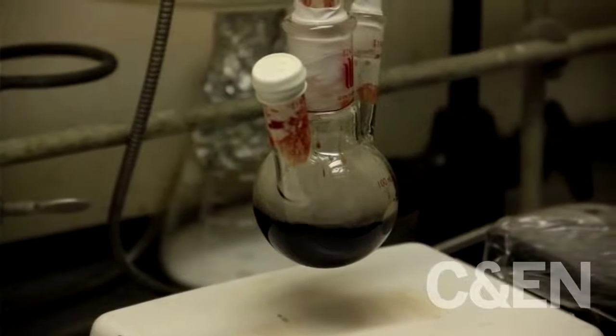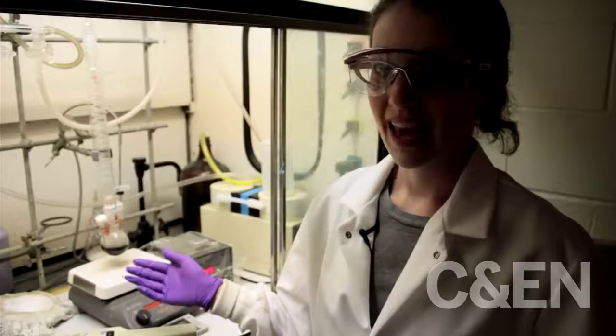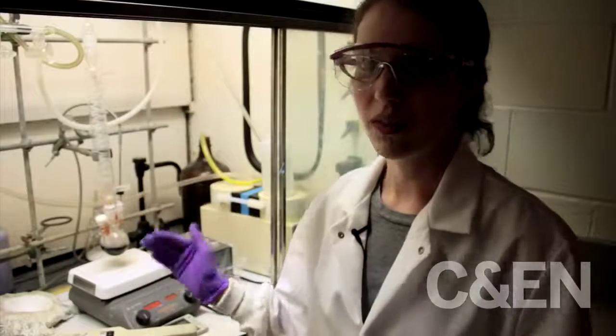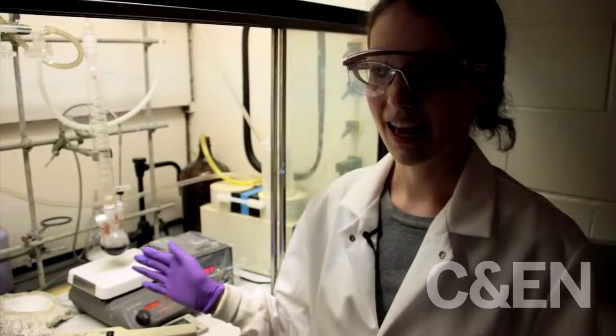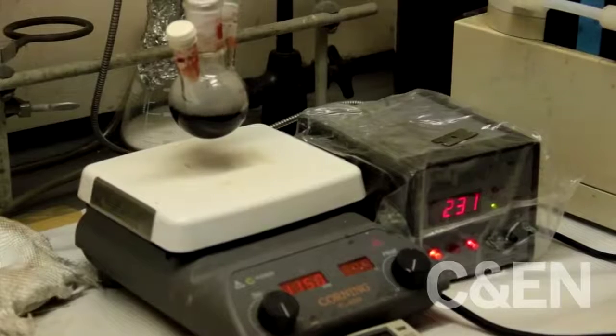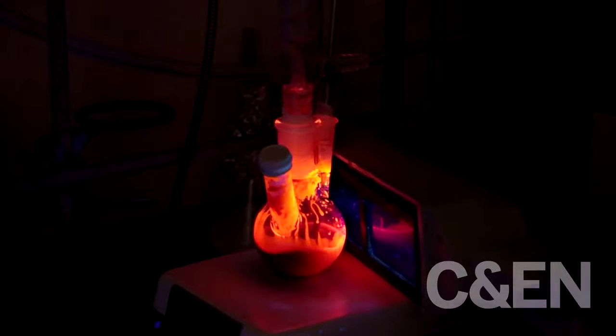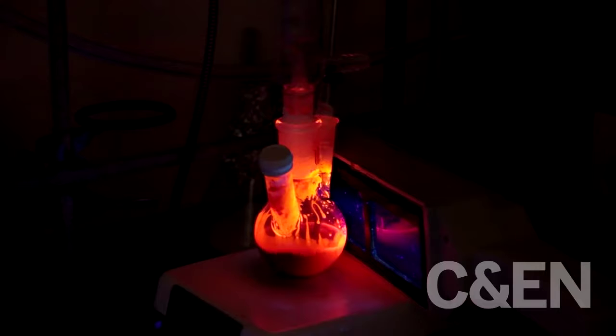At this point, the quantum dots have annealed, and so now we are able to just cool them down to a temperature where we can clean them. And as they cool, they get brighter. So at this point, the reaction is over. So if I excite them with the black light, you can see that now they fluoresce. At the lower temperatures, we're able to see the color much more clearly.